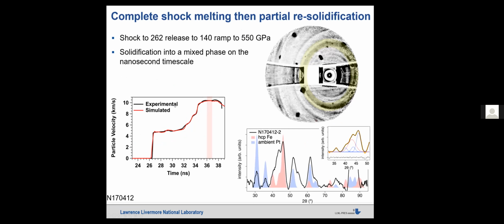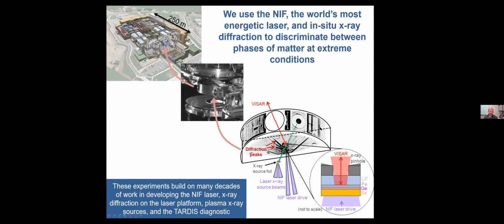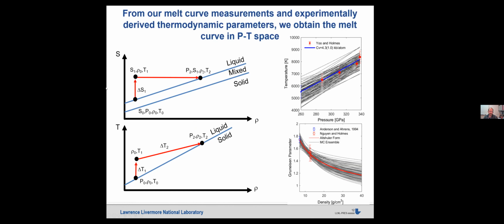So then your second point, let me get back to how we interpreted it. Your point is that entropy is going to vary as a function of temperature. It really depends upon what you want to hold constant. In this case, we made sure to be self-consistent in how we approach that. The thermodynamic paths I'm considering are ones in which I start at a reference point on the solidus, which has some initial entropy, some initial pressure, some initial density, and some initial temperature. Then I add entropy isochorically to a state that has a new entropy, same density, new temperature, and a new pressure. So I'm accounting for the fact that the pressure will change, and then I go from that density-entropy point to the density-entropy point on the liquidus at high pressure, P2, which we care about most.